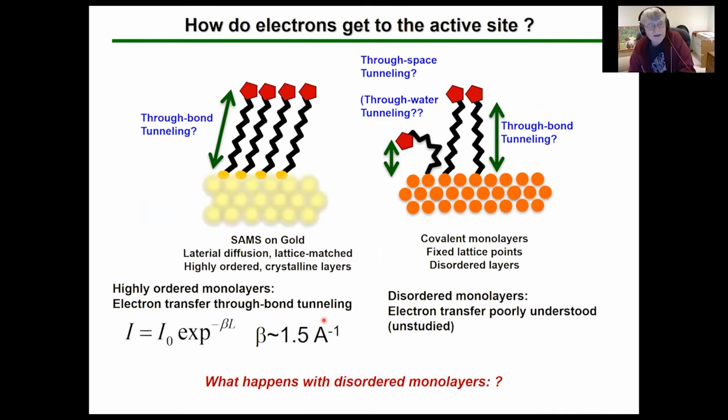Now, so again, I predicated this by another experiment that shouldn't have worked, that if we simply believed the self-assembled monolayer on gold literature, we would have said that these layers should have been insulating, and therefore we should not have been able to tunnel electrons because that tunneling process is very, very slow. So I want to make a really important distinction, which has to do with crystallographic order. So diamond samples are, of course, crystallographically ordered, but the molecular layers that form on them might not be. And in the self-assembled monolayer on gold literature, there's an accidental degeneracy between the intrinsic optimal packing distance between alkyl chains, say in a wax or other bulk material, that optimal distance is almost exactly equal to a gold-gold distance.